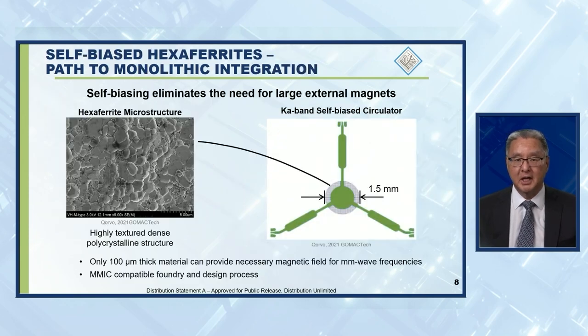A key success of the M-Cubic program has been the development of a thick hexaferrite material that possesses sufficiently high self-biased magnetic fields and is compatible with millimeter wave form factors. Thickness is an important metric, as the magnetic field strength is proportional to the volume of the material. An SEM image of the hexaferrite material is shown on the left. Significant challenges were overcome to produce the right polycrystalline structure and the 100 micron plus thicknesses, all of which are compatible with MMIC fabrication and design processes.